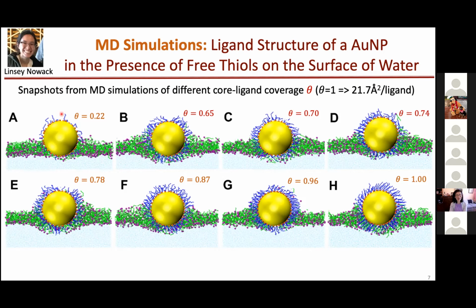This is a system of just a single nanoparticle with different ligand coverage, in the absence or presence of the free thiol monolayer. Here I'm only showing the result of the gold nanoparticle with free thiols at the surface of water.